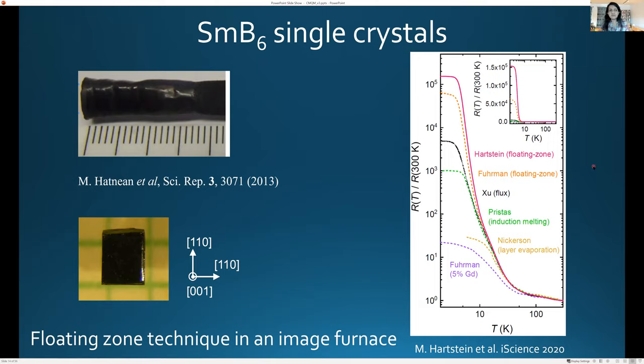So to get maybe 5 or 10 crystals with a high value of resistivity ratio at low temperatures to high temperatures, we would characterize, or my students in my group would characterize, close to 100 crystals to get maybe 5 that we would test in high field magnets to observe quantum oscillations, given that the best crystals are those with very, very high resistivities of the bulk, so where this value goes the highest, and that's our criteria for determining what the most pure single crystals are, which show the best insulating behavior.